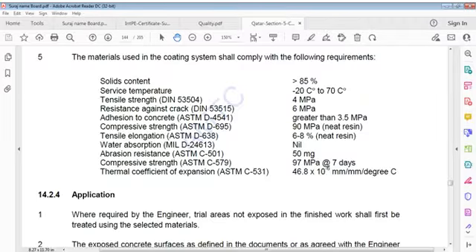Compressive strength ASTM D 695, and this is 90 MPa. That is compressive strength. Tensile elongation ASTM D 638, 6 to 8%.